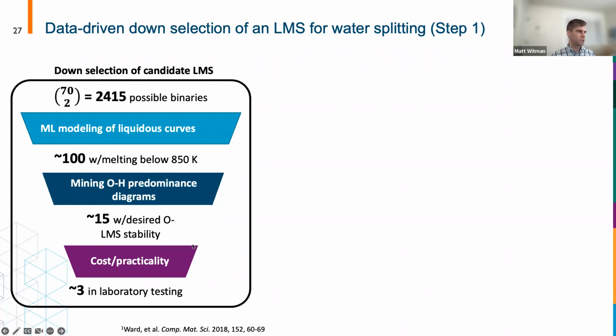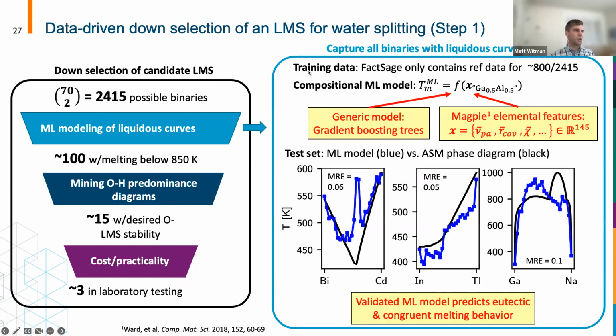lab? So first we did a simple machine learning modeling of liquidus curves. The reason why we had to turn to machine learning is we wanted to just go into FactSage or some commercial thermochemical database and get all the melting temperature, all the liquidus curves for all binaries. But there was only data for about a third of them, reference data for about a third of them. So we can just develop a quick and simple machine learning model to predict the melting temperature of a given composition, right? So in this case, you're just looking at a generic model like gradient boosting tree regression, and you can use things like MAGPIE features to derive this compositional machine learning model.